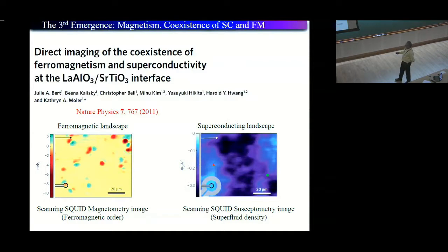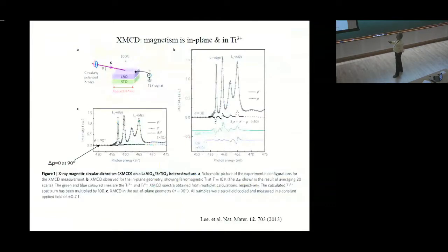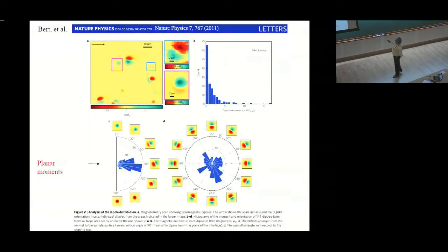You can actually touch this scanning SQUID head and carry the moments along with this head. So you can move it along on the surface. Okay, so this is also expected. There is a strong planar behavior of the moments. Moments are aligned in the XY plane, perpendicular to 0, 0, 1. There is a strong anisotropy, and so as you see, these are the counts.